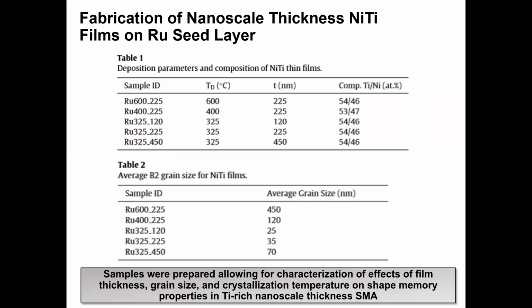So NiTi films of 120, 225, and 450 nanometers were sputtered at 325 degrees. And films of 225 nanometers thickness were sputtered also at 400 and 600 degrees, which are generally more suitable temperatures to ensure the crystallization. Each of these depositions was done onto a silicon wafer, which had been coated with a 5 nanometer ruthenium seed layer by electron beam evaporation.